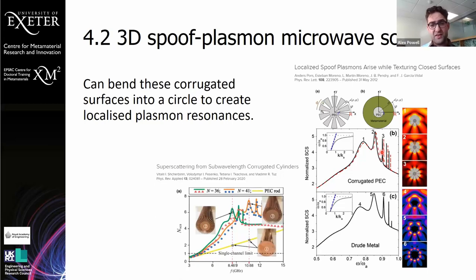So a bit later than that, people tried to make localized plasmons, which are plasmons that aren't free to travel just across the surface. They're bound to a specific perimeter. And they did this just by taking a row of grooves and ridges and bending it around into a circle, either a 2D flat shape or an extended cylinder shape. People have done experiments in both.